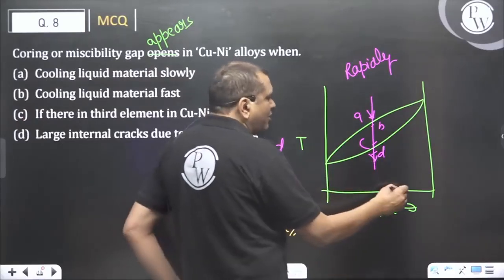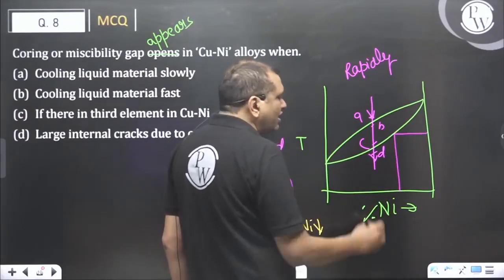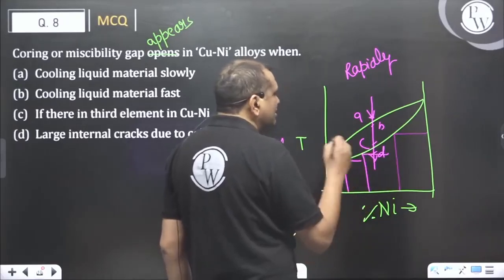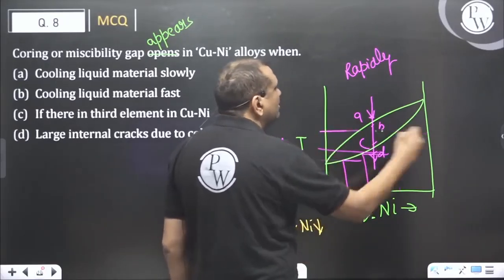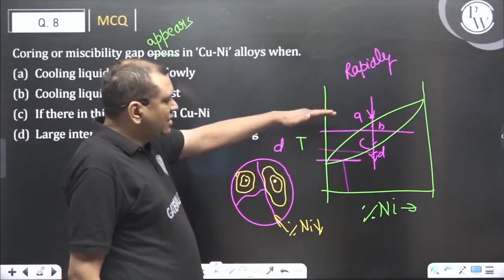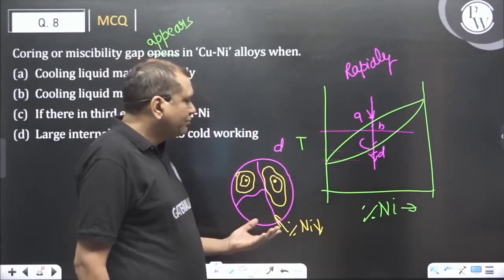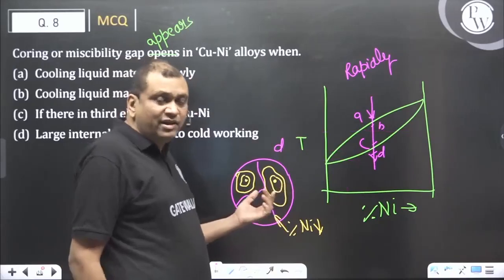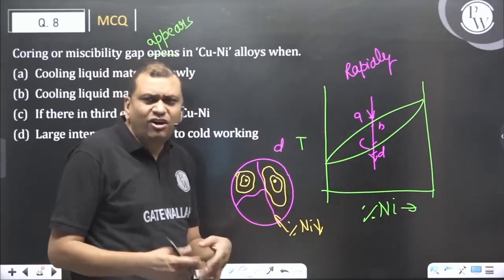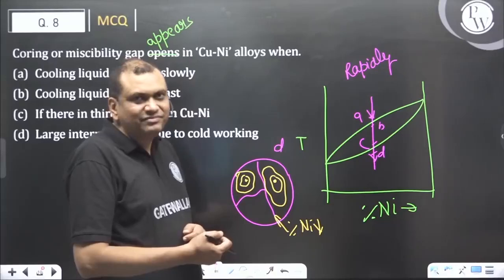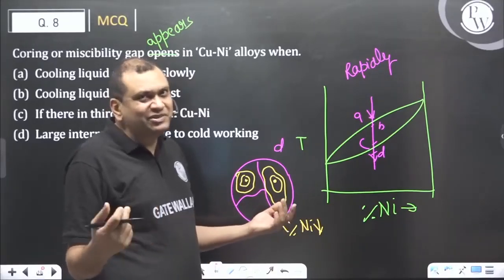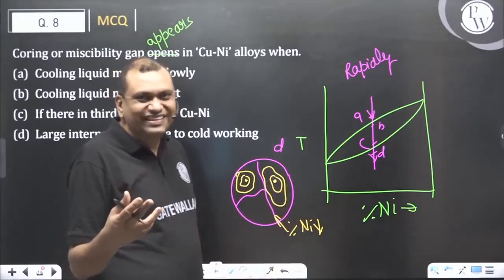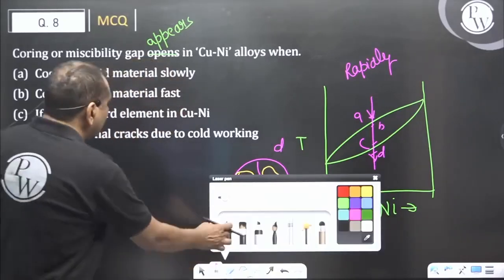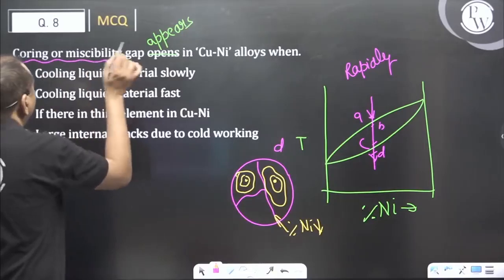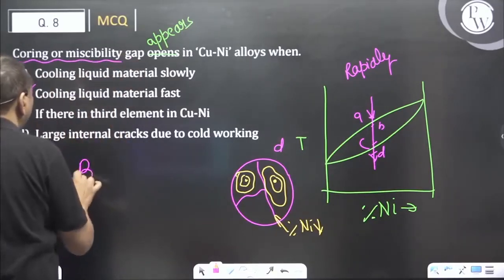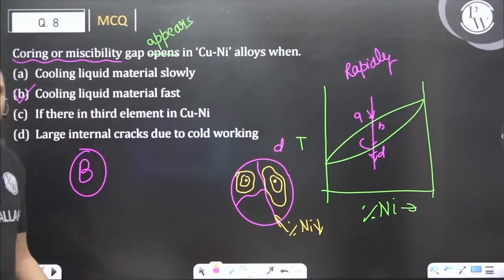And what we can see from the copper nickel phase diagram, lower is the percentage of nickel, lesser will be the melting point. See, lower is the percentage of nickel, lower will be the melting point. So at grain boundary, melting point will be low. So if you hot work the material, grain boundary material will melt out, producing crack that leads to brittle fracture. This phenomenon is called coring or miscibility gap, and it happens when we are cooling the material very fast.